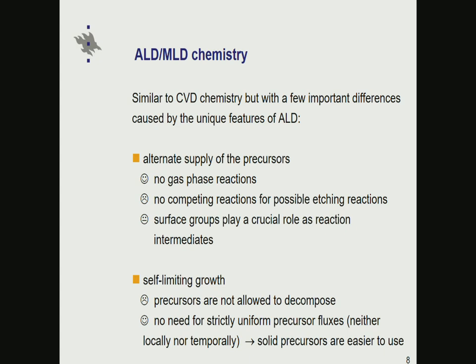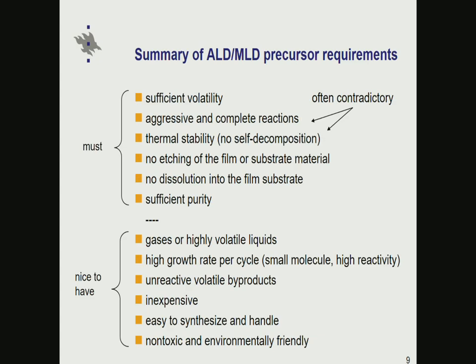It also applies temporally, meaning that the very first pulse can be larger than the very last pulse in the given process, as long as the last pulse is high enough to saturate all the surface sites. That ensures that we still get the same amount of film deposited in the last cycle as in the first cycle. That means one can more readily exploit solid precursors in ALD than in CVD. In CVD, there is a problem that once we heat these precursors, they sinter, their surface area changes, the flux coming out from the sources changes, and that causes trouble. It's to some extent problematic also in ALD, but still easier to tolerate than in CVD.